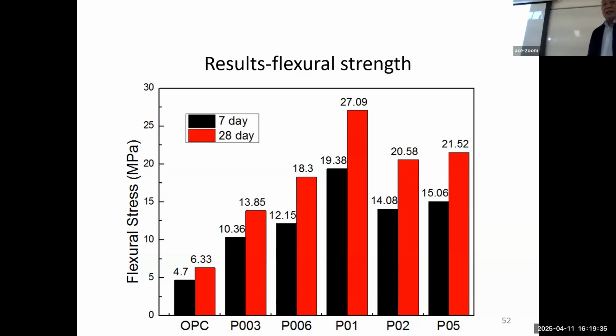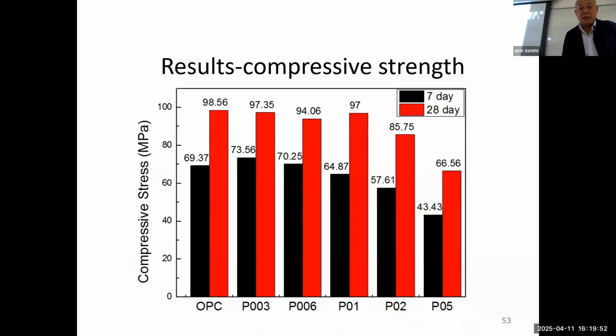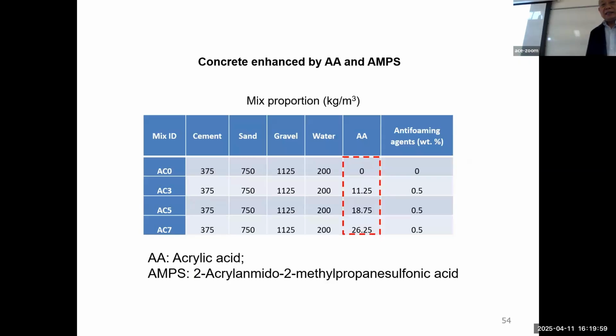And then we did the flexural test. You can see the best results we obtained: about 27 megapascal at 28 days, and for the reference it is only 6, so it's very high. And meantime, there's not much reduction in the compressive strength. And then at the University of Macau, I extended this work to concrete,